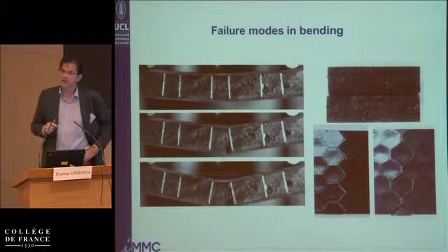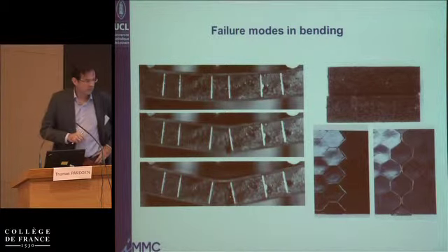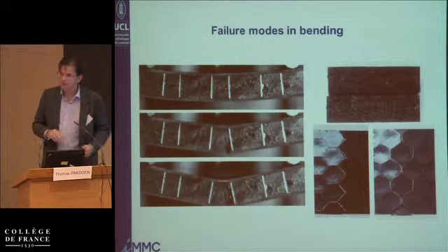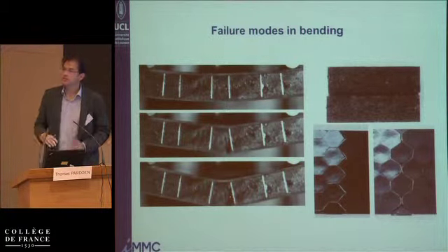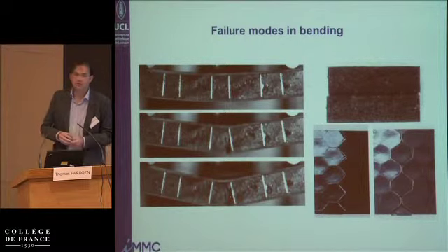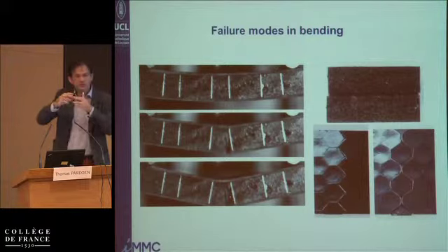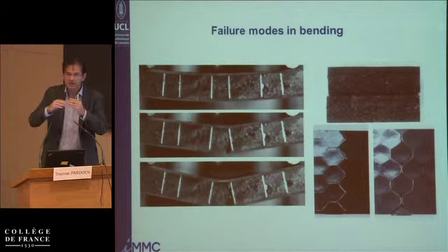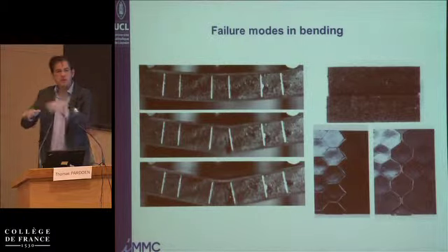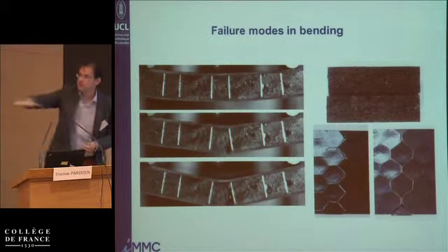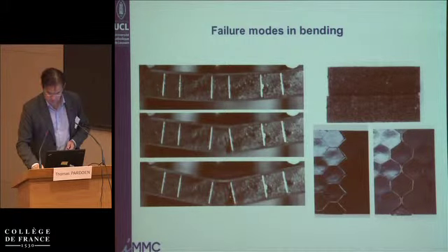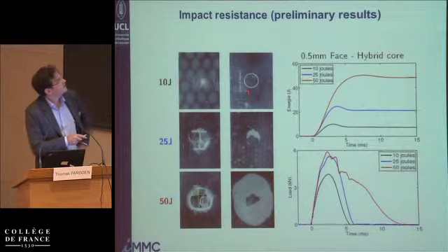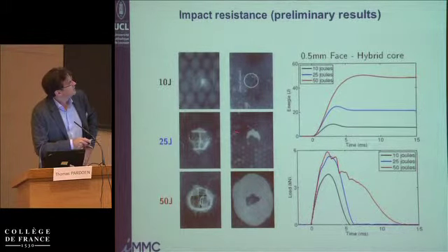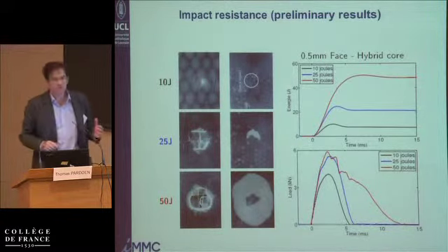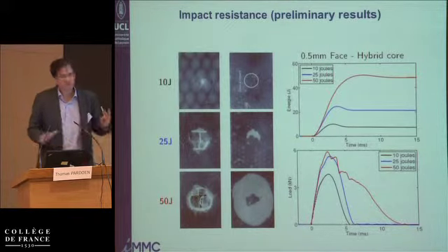Now, one good point that we realized a few months ago is that owing to the foam inside the honeycomb, it's much easier to bond the face sheet compared to the classical strategy of bonding a face sheet on a honeycomb. That makes the adhesive bonding more complicated because you're just bonding on a small edge, while when you have the foam all inside, you have a full surface to improve the adhesion. We have made some impact tests. This is just the honeycomb, and this is the honeycomb filled with the foam, and the way the load is distributed is much better in terms of energy absorption.